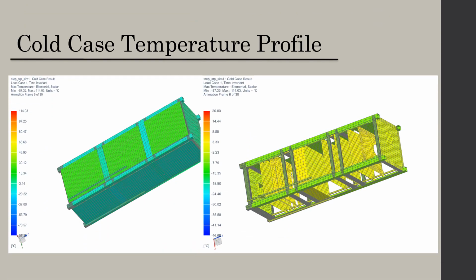The cold case result shows us that the temperature of the CubeSat ranges from negative 87 degrees to 114 degrees Celsius. The maximum temperature is on the side facing the sun, since it receives high solar flux compared to other faces. As this side heats up, heat flows to the colder surfaces and radiates away. The temperature generated on internal PCBs is transferred to other parts through standoffs. The maximum temperature on the PCB is 20 degrees Celsius.